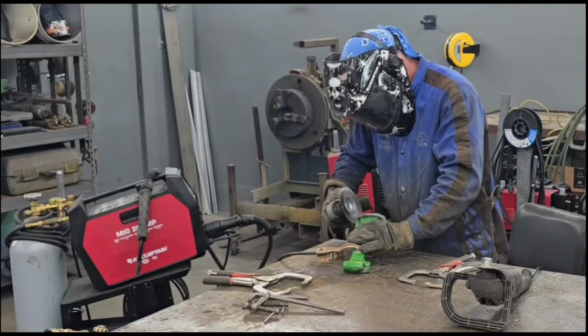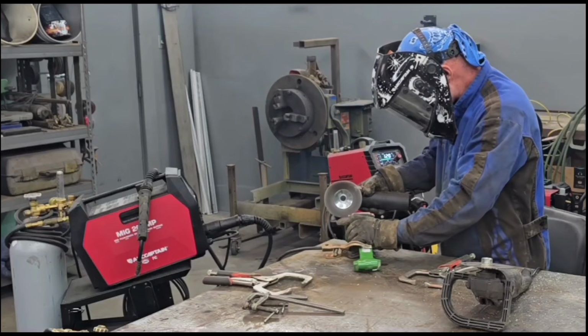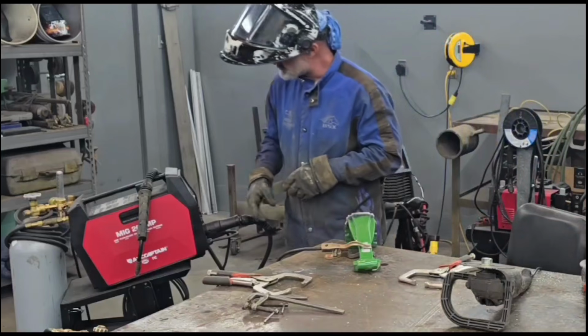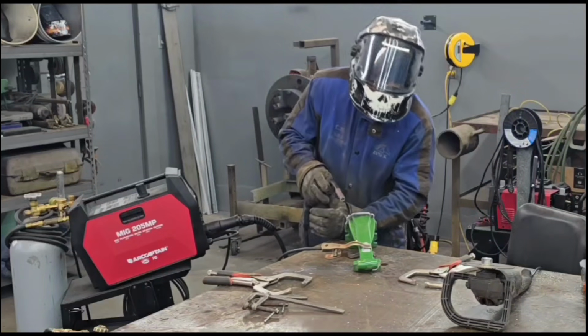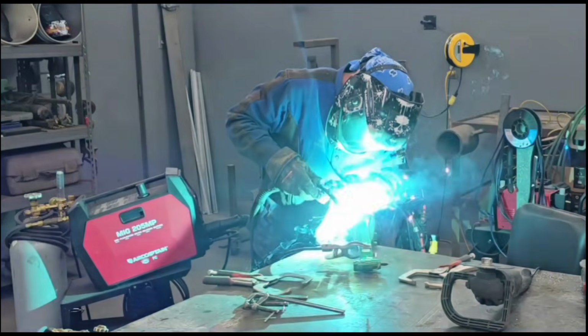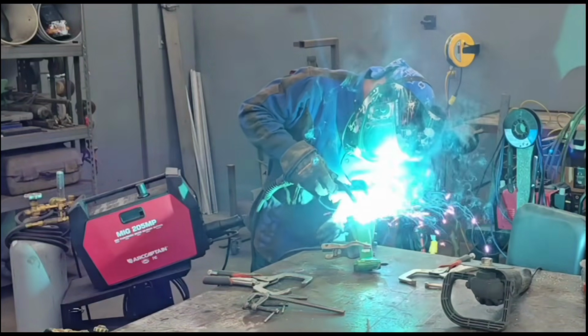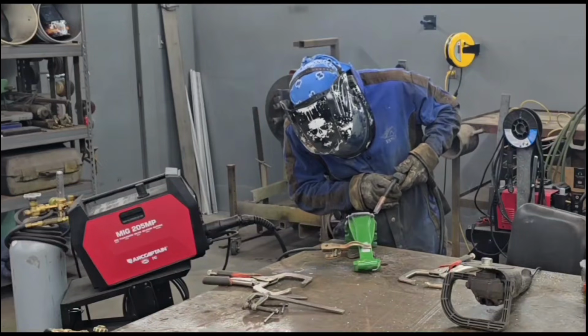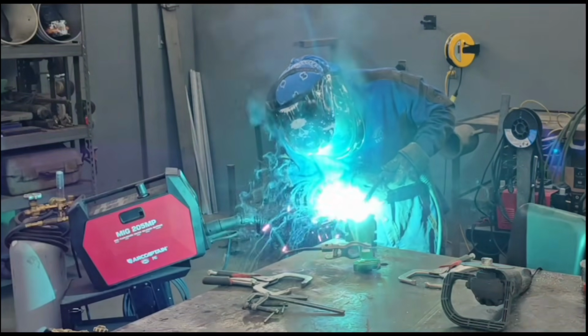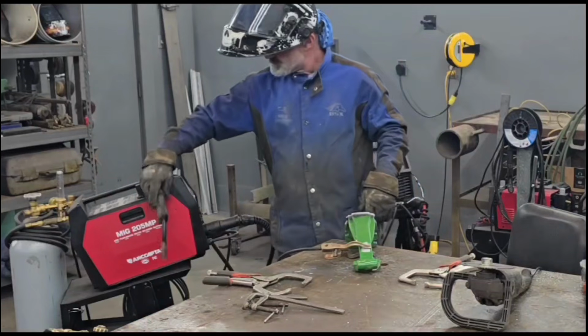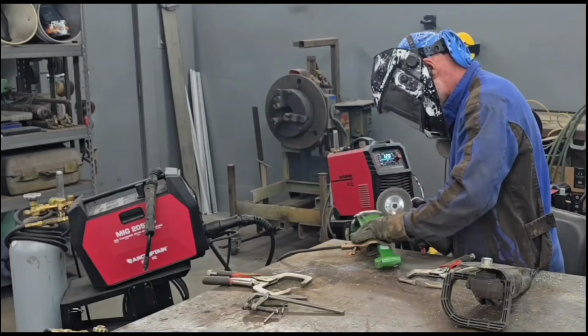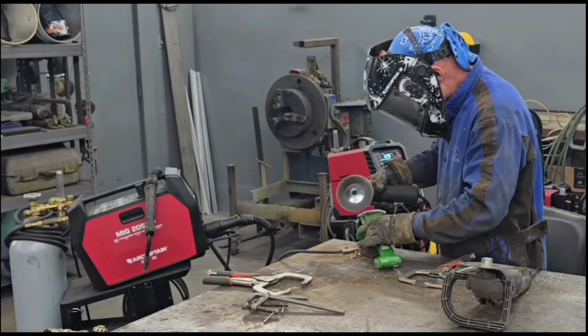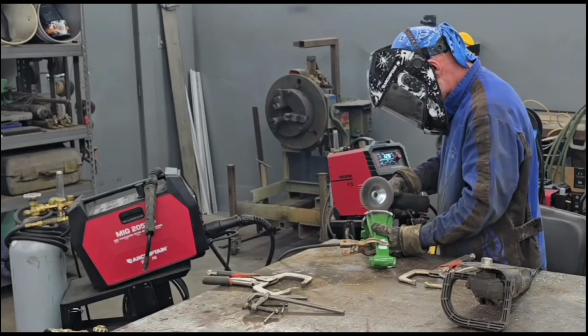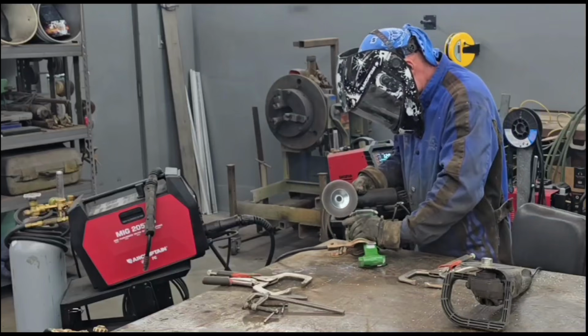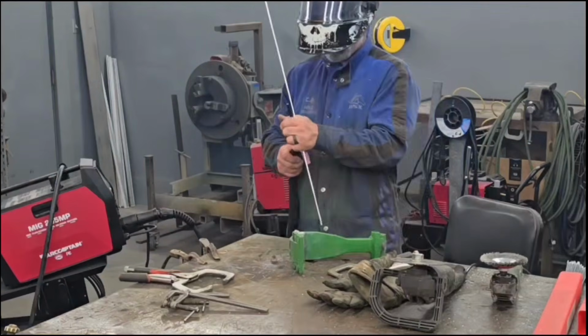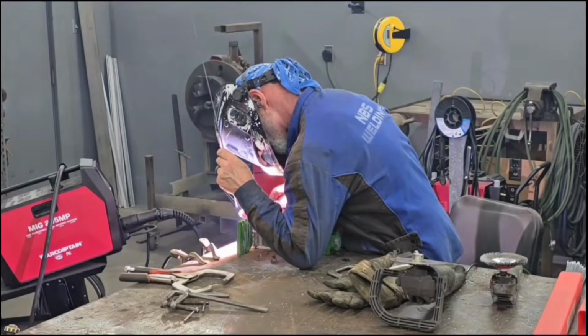You're not usually going to have really good luck on cast aluminum with aluminum MIG welding. TIG works better because there's a lot of porosity in the cast. You're going to find contaminations, and if you TIG weld on AC, when you hit that contamination, you can kind of stop and flow it out with your argon gas and get rid of those impurities. But as slow as the TIG welding is on a big thick bracket like this, if I can get some weld in there with the pulse MIG, it's going to be a help time-wise to make this a more economical thing.